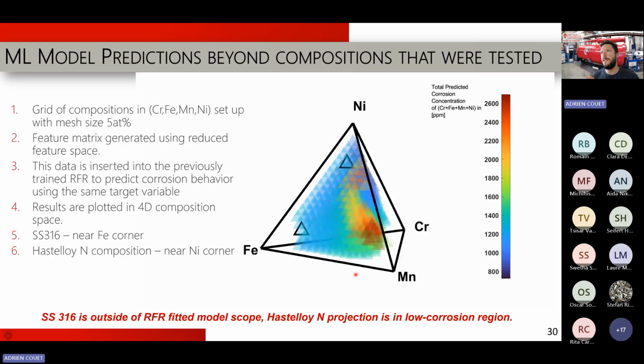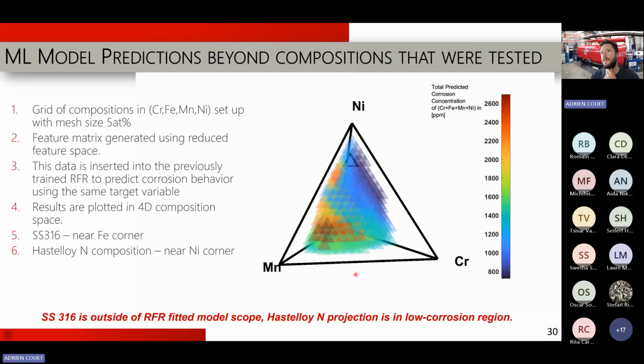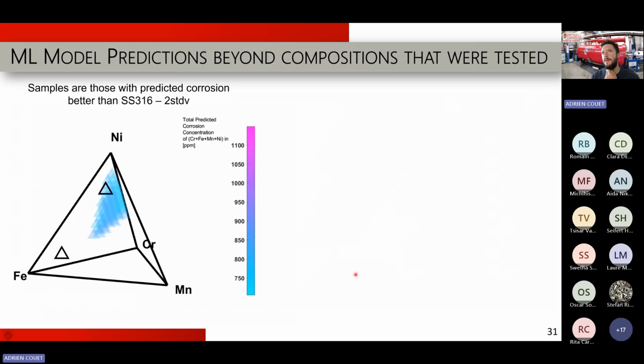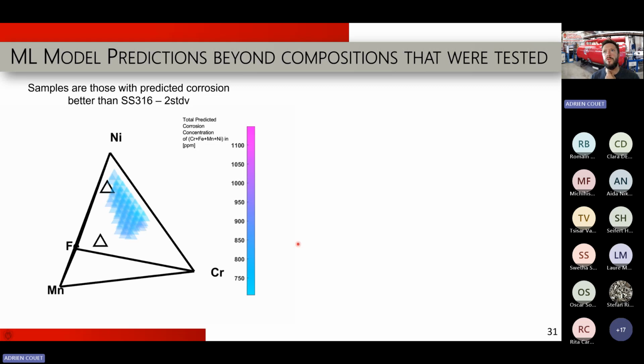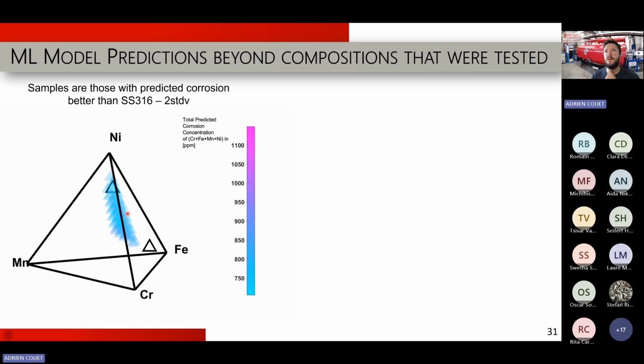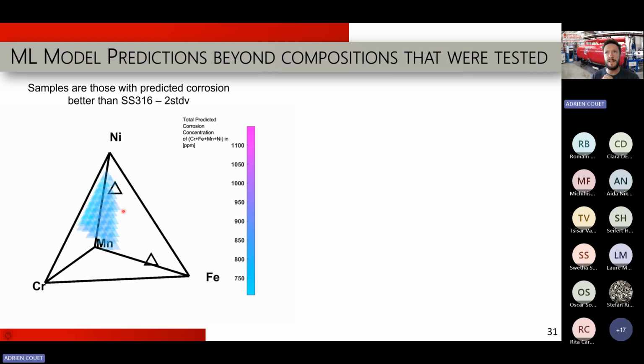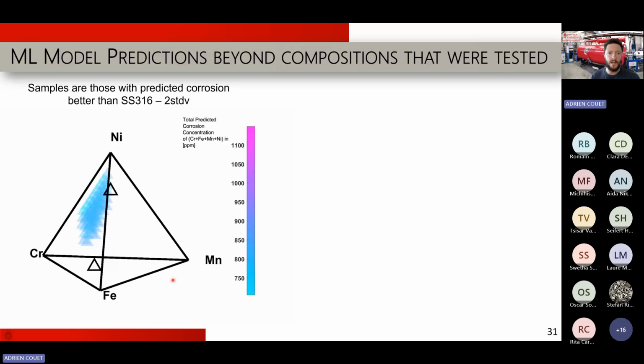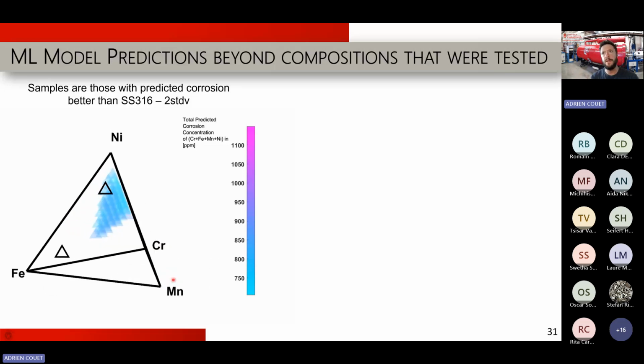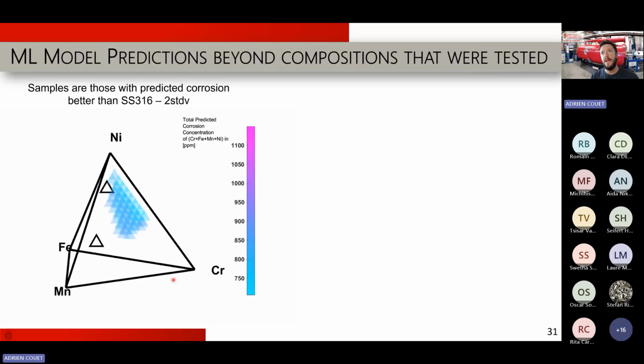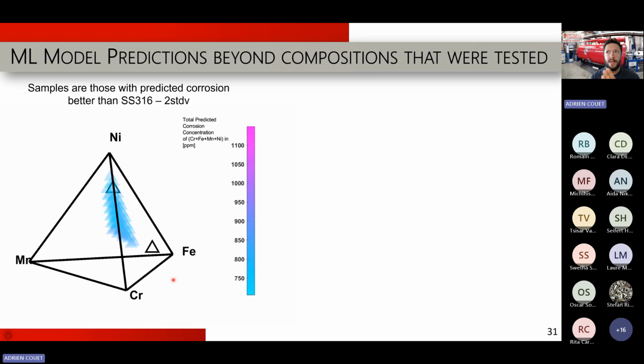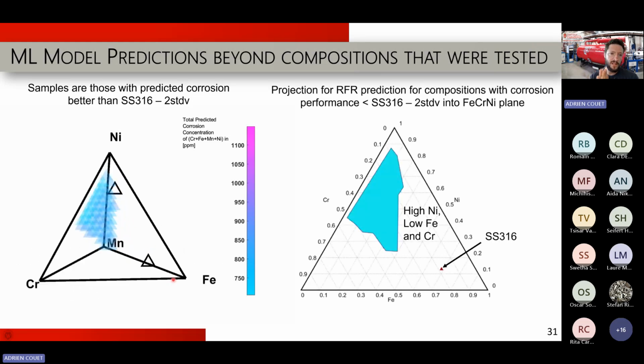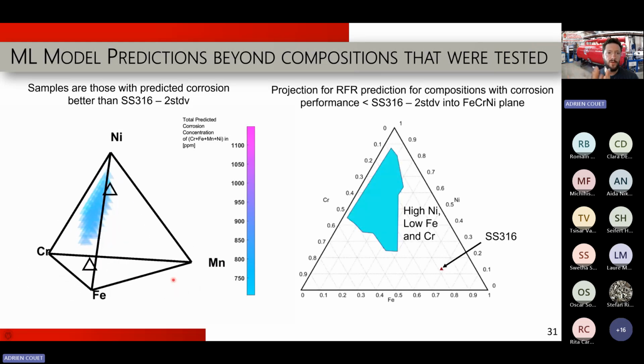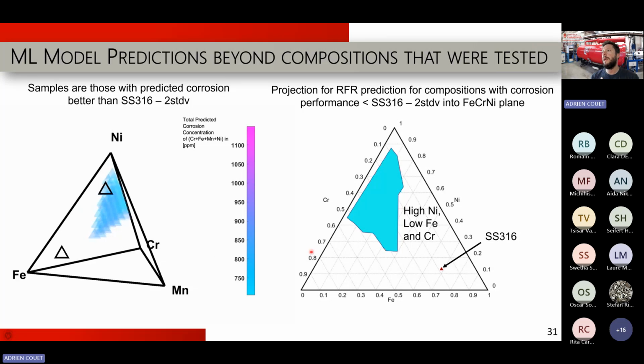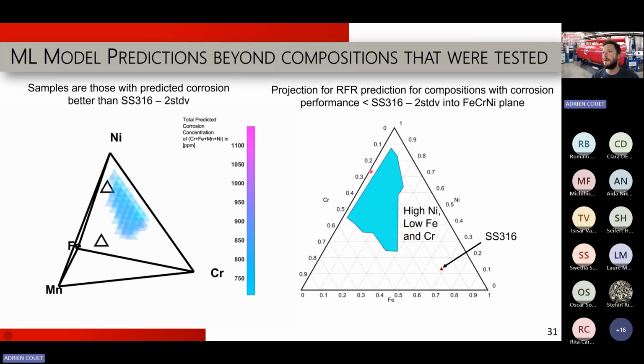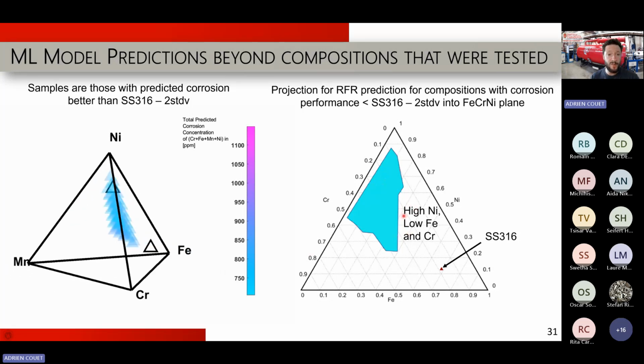And the idea is, can I find, for instance, alloys that are behaving better than stainless steel 316? So you see that the alloys that are behaving much better than 316 stainless steel are here in blue. 2 standard deviation better than this 316, and they're very low manganese, so we can almost consider them as a plane. So we have projected them on our ternary diagram, and you see that these elements here are predicted to be better than stainless steel.